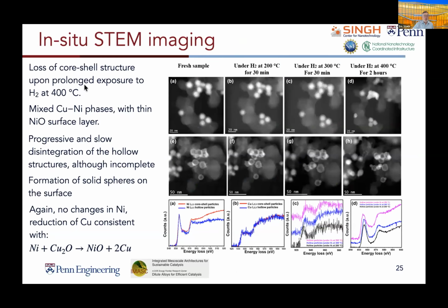All right. Yeah, so we're basically saying, we got pure hydrogen at 400 degrees C, right? We see that there's this change where the copper and the nickel mix well, but they form this nickel oxide on the outer surface. So it appears as though we start off with this pure nickel. We had the copper oxide present in the first case. And what's happening instead is that the oxygen is preferentially moving towards the nickel and away from the copper in this environment. So it's as though the existence of the copper oxide at the beginning provides the source of oxygen for the nickel oxide that forms. And that's just the observation we have.